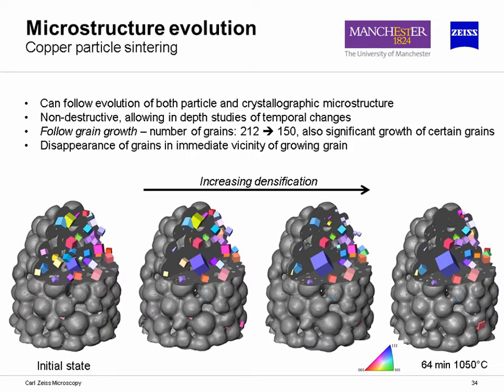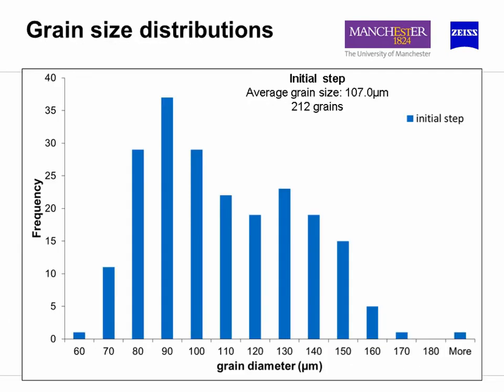And really the direction that this is going is courtesy of some work being done jointly at the University of Manchester, looking at the growth of sintered copper particles that underwent different heat treatments. But again, we're doing this non-destructively, so we can now explore the growth of individual grains or the statistical orientation change that occurs between different types of grains, and really populate our understanding of models to help understand what the drivers of growth here and change in the microstructure are.